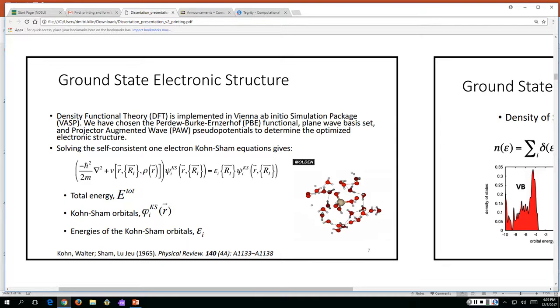And so the first way that we can take a look at what the electronic structure looks like in the material is to look at a density of states. The density of states describes where in energy are the available electronic states that may or may not be populated. And so the spectra on the bottom left shows a red-filled set of energy states, which is the valence band. And then there's an unfilled, empty set of states, which is the conduction band within the system. Having an idea of how the states are relatively separated and sorted can give us an indication of what types of optical energies are going to be needed to promote an excitation and also corresponding emission events.